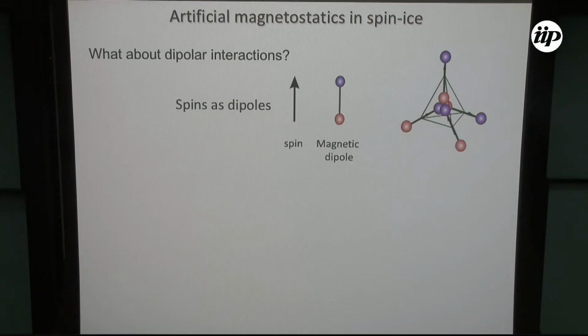And then you see that this idea translates pretty easily, in the sense that what you're saying is that if I have 2 spins pointing in and 2 spins pointing out, the charge inside one of these tetrahedra is going to be neutral. So it's going to be 0. So this already gives you 2 things. It gives you one easy way of seeing that even in the case of dipolar interactions, the picture survives, and it also gives you the extent to which it survives.